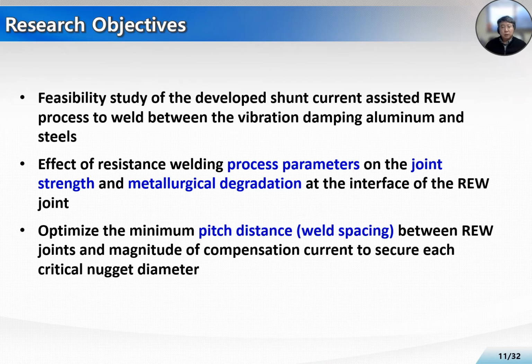The first objective of this research is the feasibility study of the developed shunt current assisted resistance element welding process to weld between the vibration damping aluminum and steels. Second, the effect of resistance welding process parameters on the joint strength and metallurgical degradation at the interface of the weld joint. Third, optimize the minimum pitch distance or weld spacing between the resistance element welding joints and the magnitude of the compensation current to secure each critical nugget diameter.